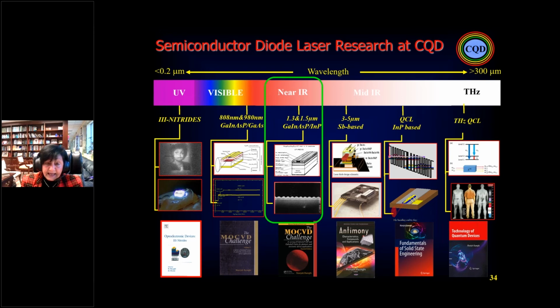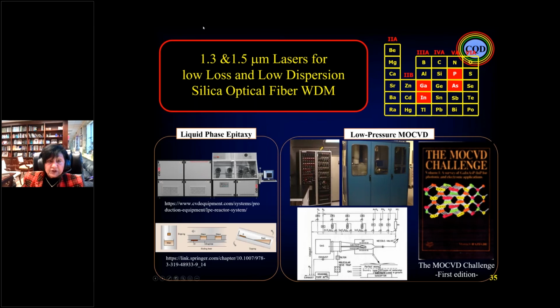But what was again the problem? It was using liquid phase epitaxy or vapor phase epitaxy, and it was impossible to have the DFB. All of the information is in this book, The MOCVD Challenge. For the 1.3, 1.5 micron, which is for the silica optical fiber, they were using liquid phase epitaxy, and that was the problem. You cannot grow the wide band gap material, indium phosphide, on gallium indium arsenide. So it was a big problem.